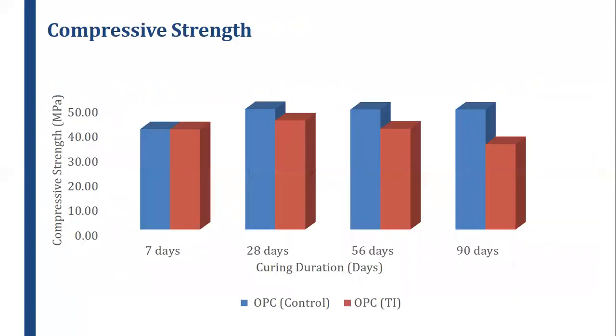The compressive strength, on the other hand, was monitored for 90 days, and it is clearly shown that the mortar prism prepared with the Bacillus intermedius bacteria showed deterioration, or rather a decline, in compressive strength from the 28th day up to the 90th day. The extreme deterioration was observed on the 90th day, where the mortar prism prepared with the Bacillus intermedius bacteria reported low compressive strength as compared to the control mortar prism.